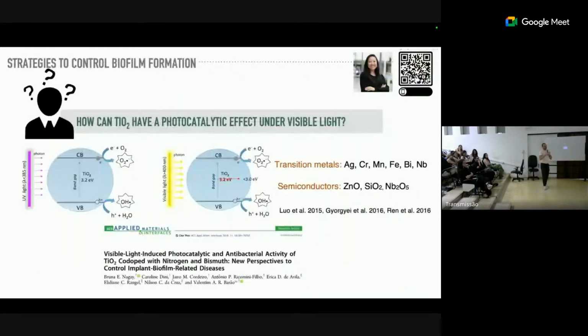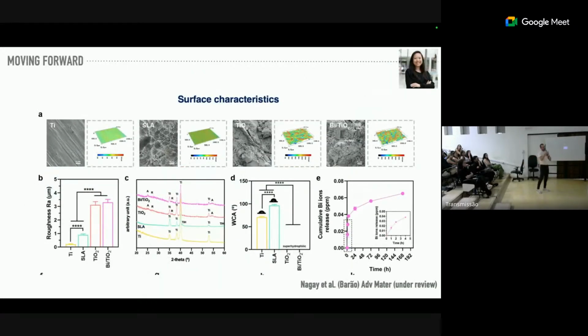I didn't show the main results of this paper because in 2019, we used this technique to have an antimicrobial effect, but the effect was not so high. But it was our first study, so the effect was like 1 log reduction. In terms of antimicrobial effects, not so high. We also had to apply the light for 30 minutes, so that is too long. Well, but we moved forward, and now we have some data that is not published yet.